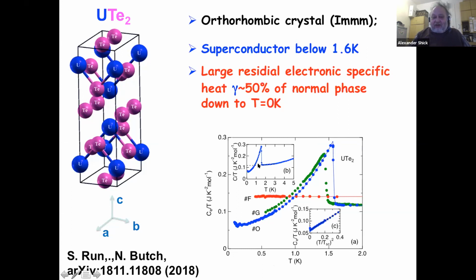And actually they show it like here. You see, this is like 50%. Well, later on, it turned out that they just didn't cool down low enough, because at the end there is this race, but then the specific heat goes to zero. So this initial excitement eventually was not really so well justified, but anyway, it's an interesting material.